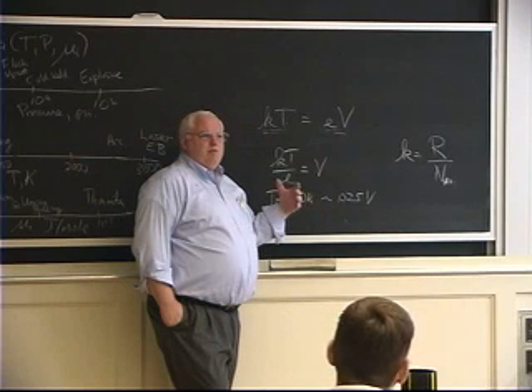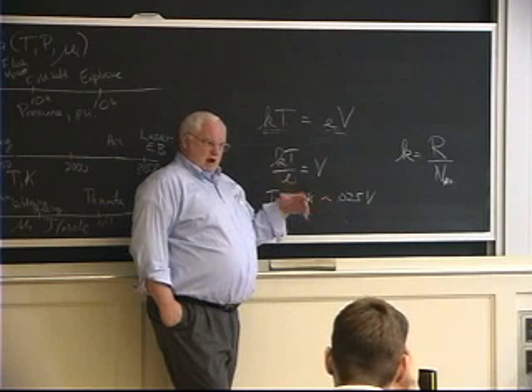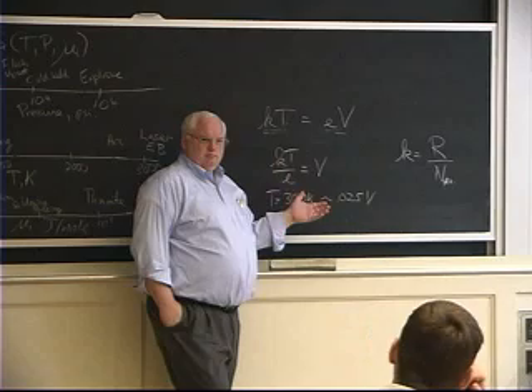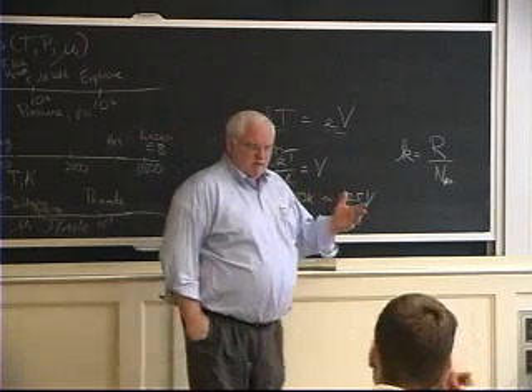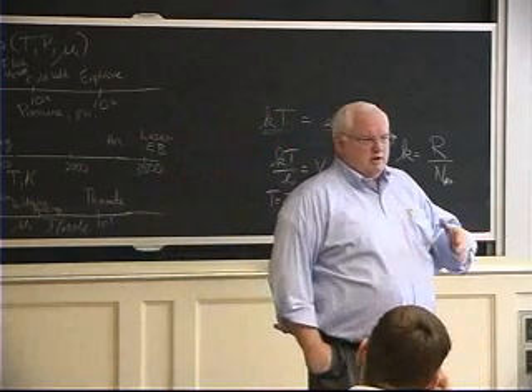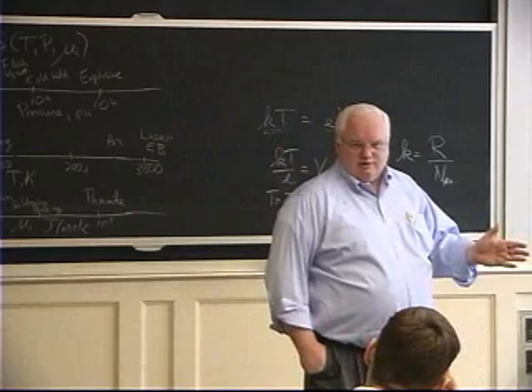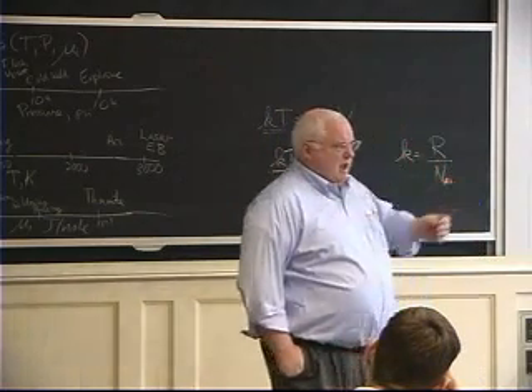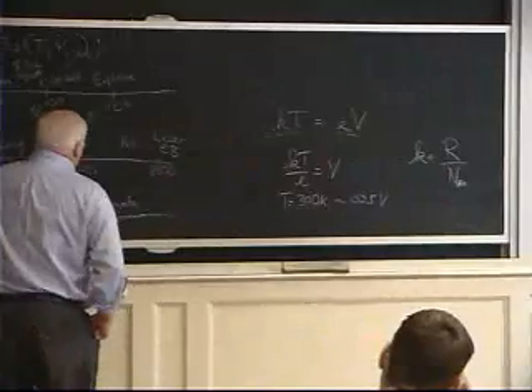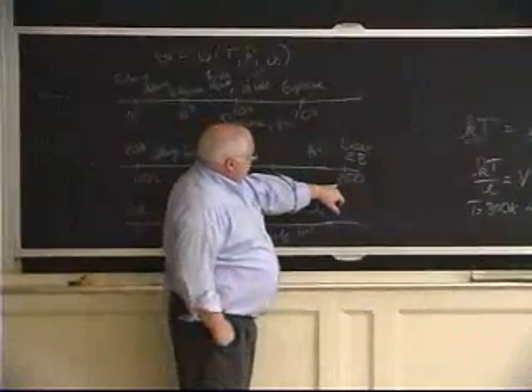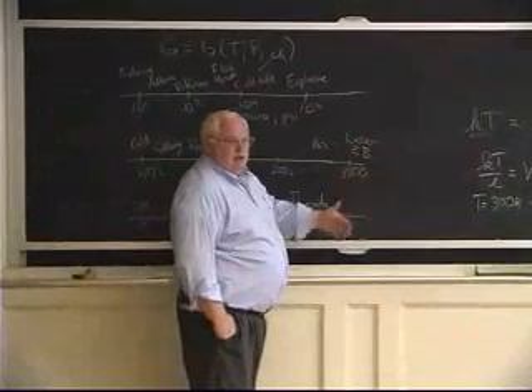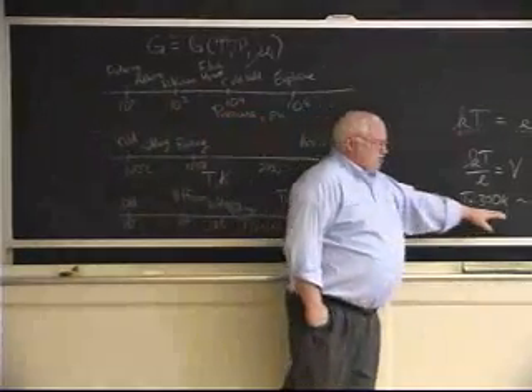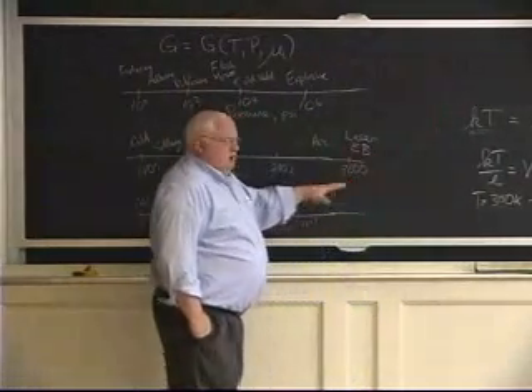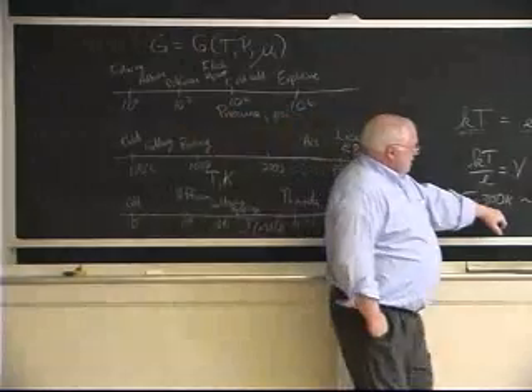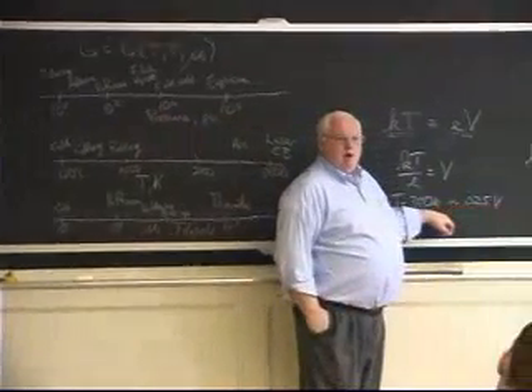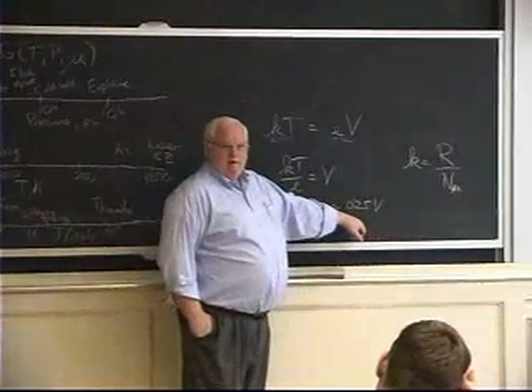So I can start breaking primary bonds if I have 12,000 degrees. Well, we know we break primary bonds at 12,000 degrees. There's very few things that remain solids or liquids at 12,000 degrees. They break the primary bonds and become gases. You don't have to get 100% of the bonds broken to have something break from being a solid. You only have to have about 10% of the bonds break, so at much lower temperatures than 12,000 degrees. But I just proved to you on first principles that I can break primary bonds, nearly 100% of them, if I have 12,000 degrees of temperature.